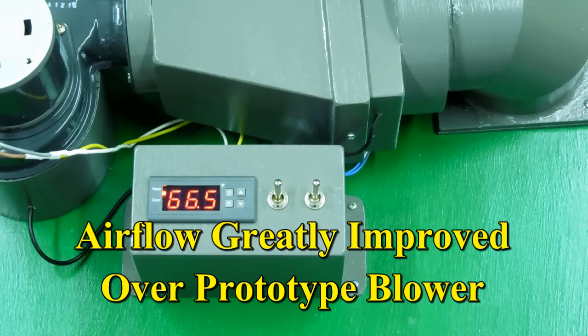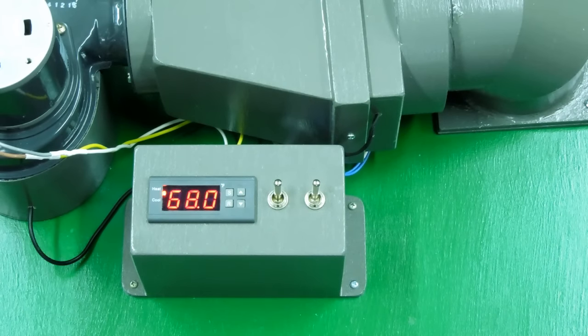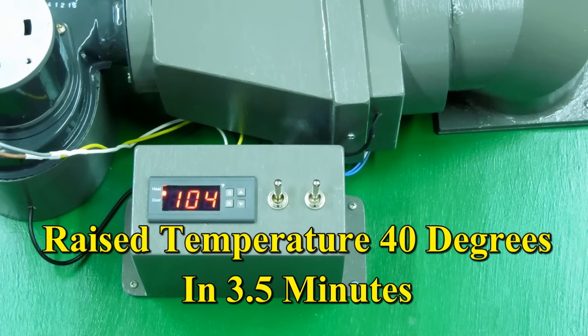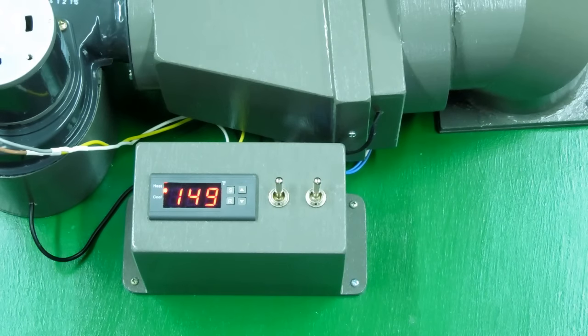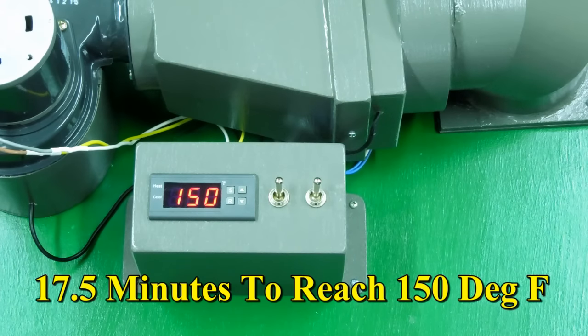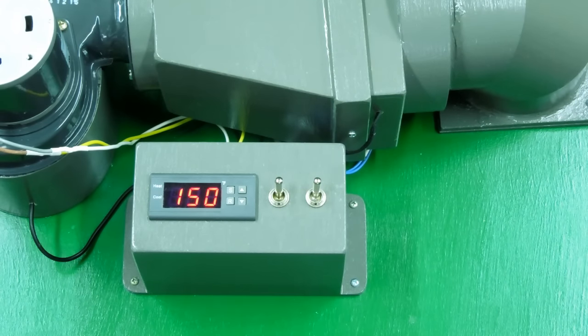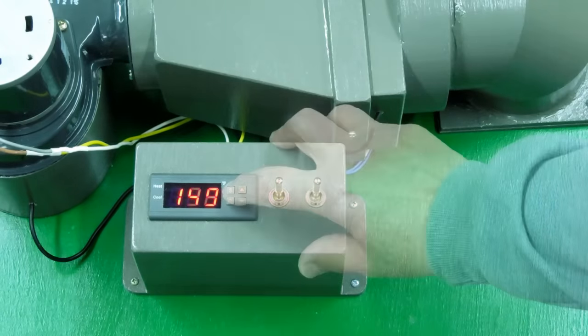The squirrel cage blower is pretty quiet. We're just going to let this run and see how long it takes to climb to 150 degrees. We need to remember we're not heating just the air that's in the box. We have to heat the box itself and any contents that are in the box. It raised the temperature 40 degrees in 3.5 minutes. It took a little over 17.5 minutes to go from room temperature, 64, 65 degrees, up to 150 degrees, and that's using both elements.